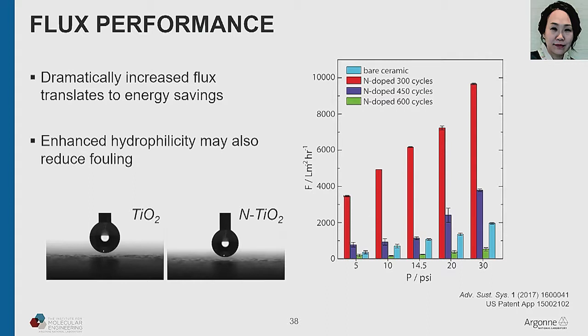Now, we're doing ALD on this thing, so we're narrowing the pores in a controllable way, but we're narrowing them. You would expect flux to go down because it goes as a power of the radius of the pores. But you can see in the red here that we see a dramatic increase in the flux of water going through this membrane once this coating is on it. Counterintuitive. If you continue to put more and more cycles of ALD and you constrict those pores enough, eventually it will drop down below where you started, but only when you've really seriously narrowed the pores. So you can get a dramatic reduction in the energy cost to push a fluid across this membrane this way.